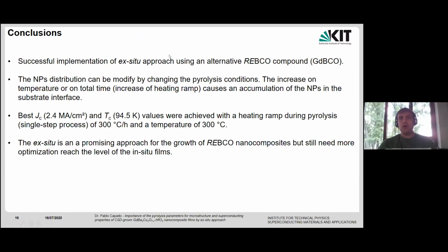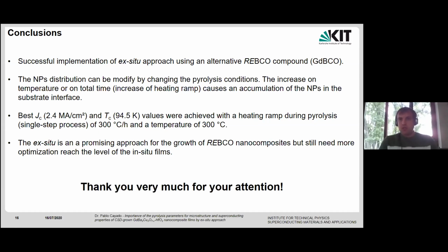Yeah, we are able to implement the ex situ approach with an alternative REBCO, because until now all the experiments with the in situ were done with YBCO, which we tried for the first time with another REBCO. And as you can read here, modifying the pyrolysis conditions can create an impact in the nanoparticle distribution. So that is something to be attentive to in the future when we want to optimize these films. So thank you very much, and that's all.